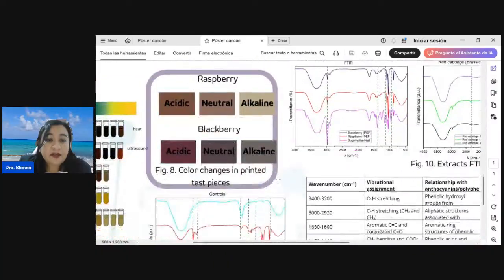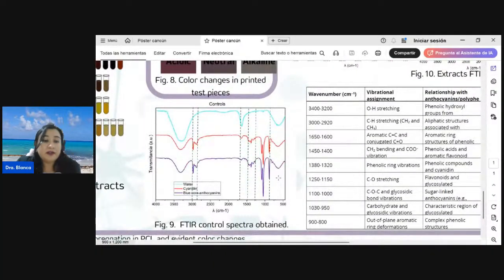For the results with the FTIR control spectra, we obtained first the controls. We use 3 controls: water, obviously, cyanidin from Sigma, and blue corn anthocyanins. This anthocyanin was provided by another laboratory, and in this case, the anthocyanins of blue corn were purified. So in these 2 patterns, we can find the signal of the anthocyanins.